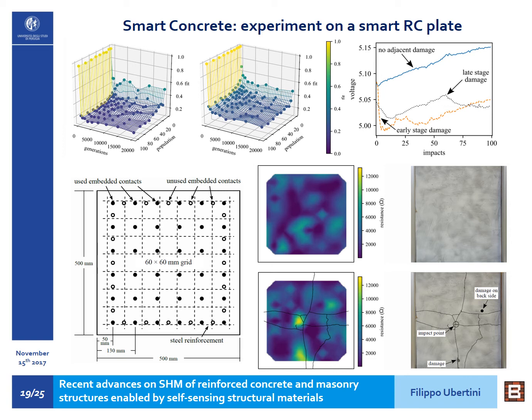But after application of 100 hammer hits, the plate is damaged, and in particular there are 3 points of most prominent damage: the impact point in the center, a damage on the back side, which we don't see from this picture, but it's indicated by a black dot, and another damage that's a sort of spalling on the bottom part of the plate. And clearly in these regions we have a local increase in the values of the properties of the electrical resistors that we achieve after solving the inverse problem. So what we can conclude here is that a resistor mesh model like the one proposed can allow a damage detection and localization in a smart concrete structural component such as a plate.